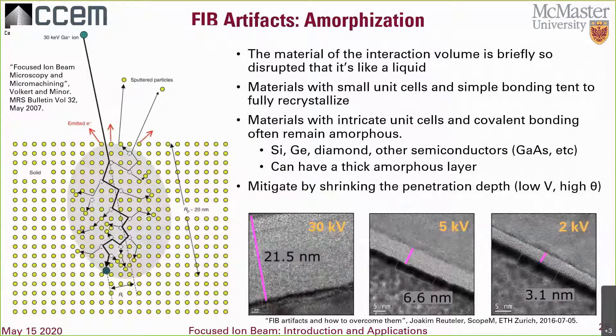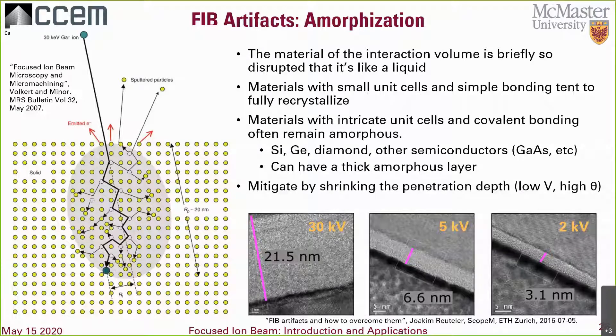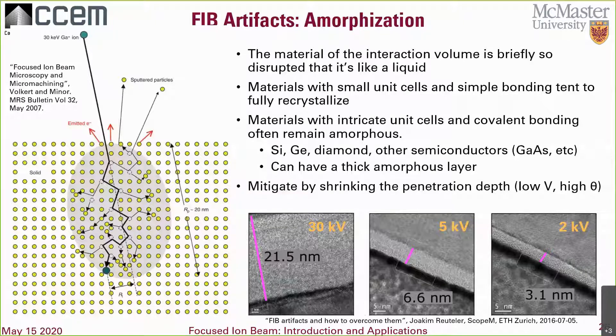Another artifact is amorphization. For a brief moment of the ion-to-solid interaction, crystalline material in the interaction volume is so heavily disrupted it's basically like a liquid, just for a brief moment. Materials with simple unit cells and bonding, like metals, tend to resettle back into their natural crystallographic arrangements quite well. However, more intricate unit cells are less likely to recrystallize — especially if the bonding is covalent, as in silicon, germanium, diamond, and other semiconductors like gallium arsenide. This amorphous state is metastable, and for those materials the amorphous layer will be thick. Its thickness can be reduced by shrinking the penetration depth.